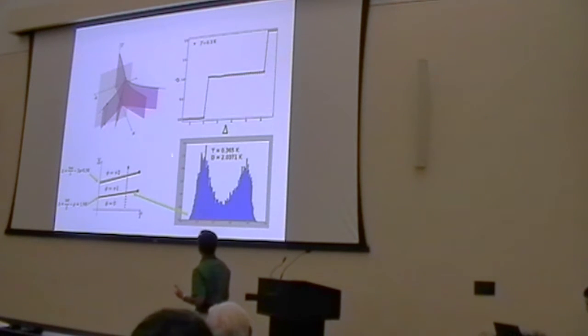So holmium iridate has a double pyrochlore structure, with the iridium ions forming a pyrochlore structure with an all-in-all-out order. The all-in-all-out order provides you exactly this staggered chemical potential within the monopole picture. It's a powder sample, there's no phase transition, but as you reduce the temperature, the magnetic moment in the all-in-all-out phase increases, and it saturates at exactly half the total moment, and this is absolutely consistent with lying in this part of the ring.